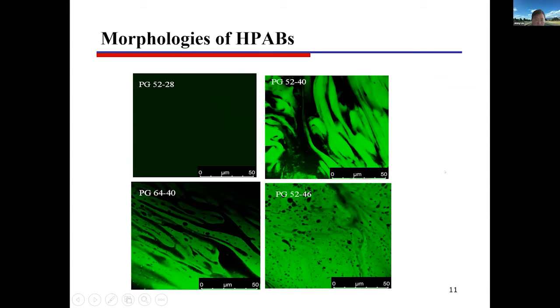And this is the result from fluorescence microscopy and morphologies of HPABs. You can see for the unmodified binder, basically only one phase can be observed. However, if we look at the other three types of HPABs, a biphasic physical structure can be found. You can see for PG52-40 and 64-40, basically the polymer formed a continuous phase, implying adequate compatibility between polymer and asphalt. And it's very clear the polymer phase was the dominant phase for the highly polymerized asphalt binders, and you can also see this in the PG52-46.